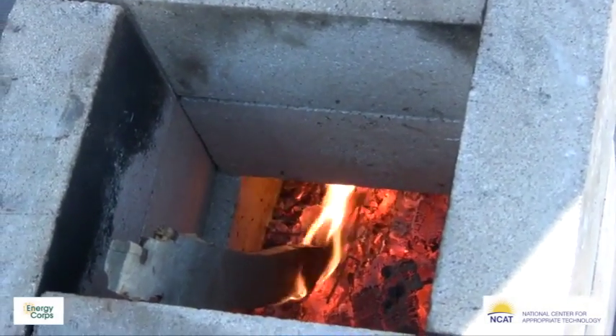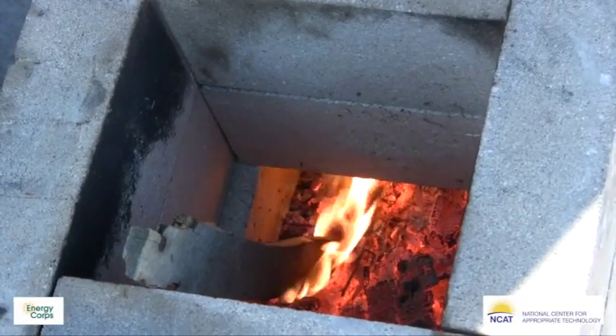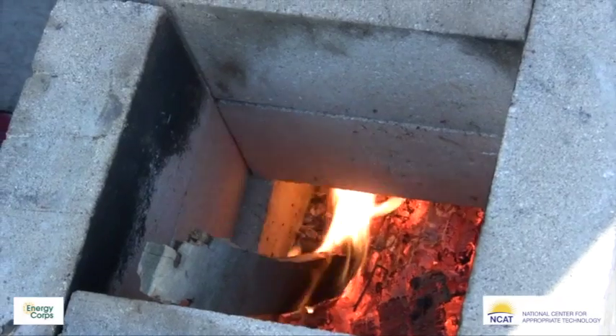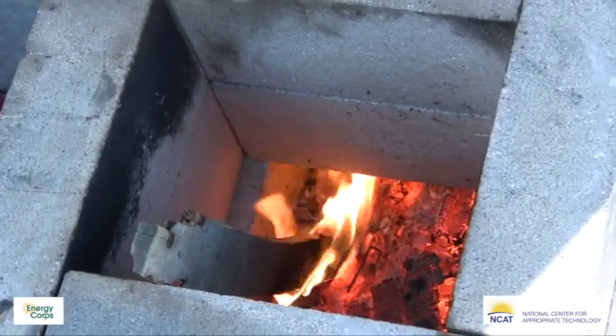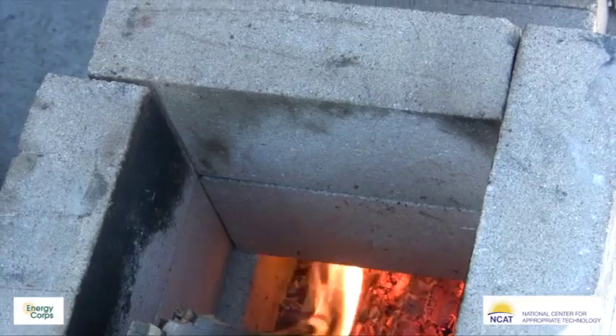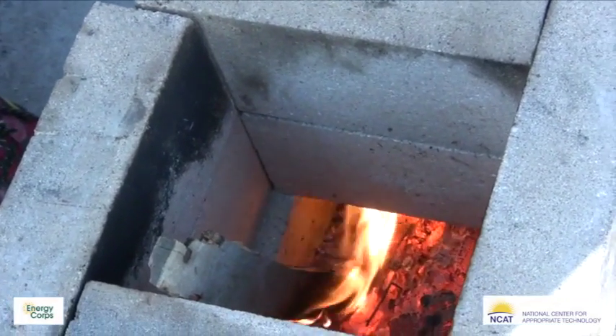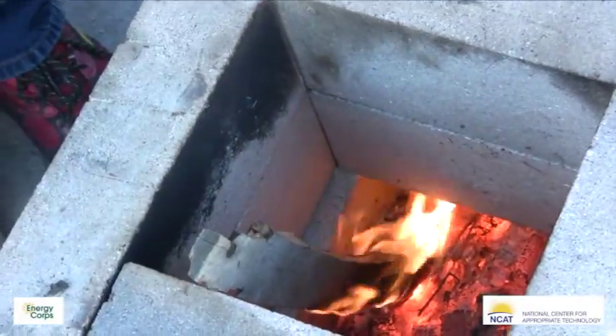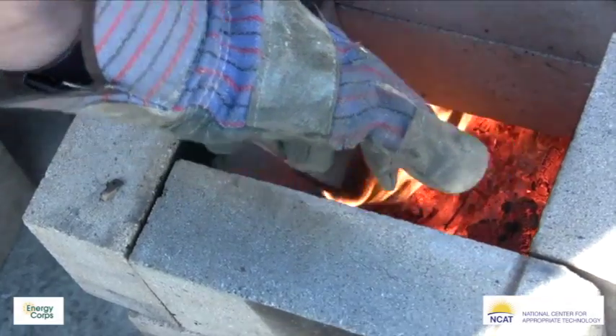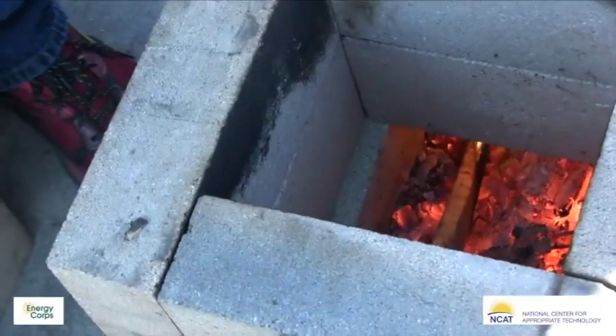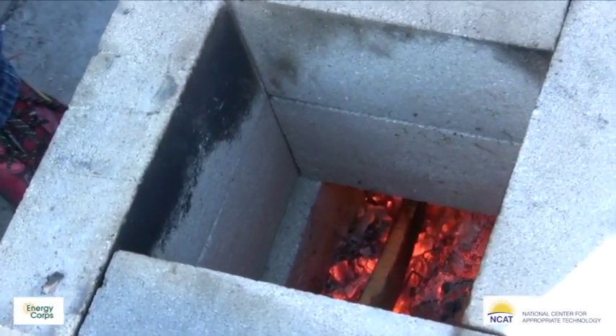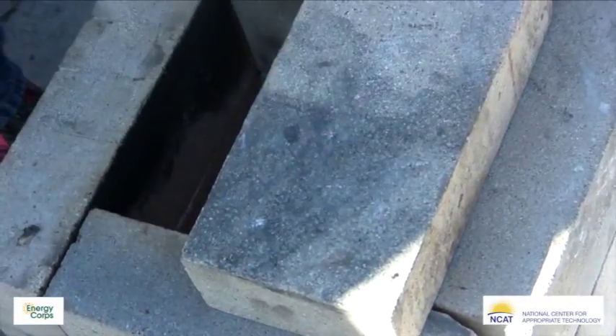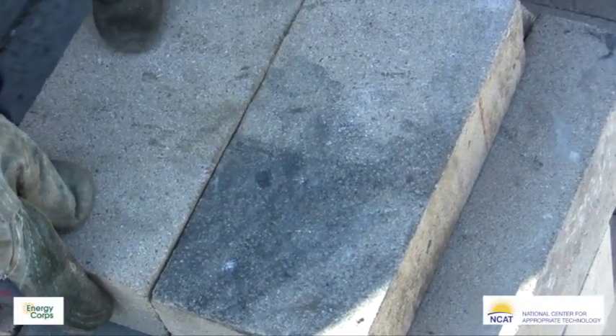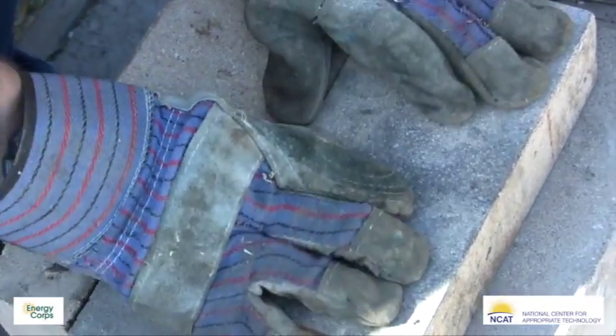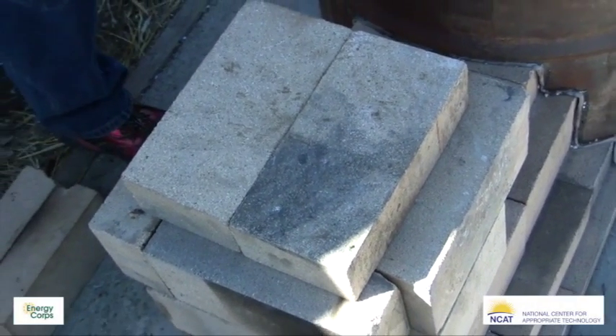The fire bricks themselves are very strong as far as their ability to take really high temperatures, but they're also very brittle. And so if you spray water in them, then they absorb that water, and then once they get hot again, that water can turn into steam and can actually cause the bricks to crack. So the best way I have found to extinguish this is to take 2 more fire bricks and just deprive the whole system of oxygen. And just put your bricks over so that no air can be in the intake, and that'll close it off. And then you'll do the same thing on top of the heat riser once it cools down a bit.